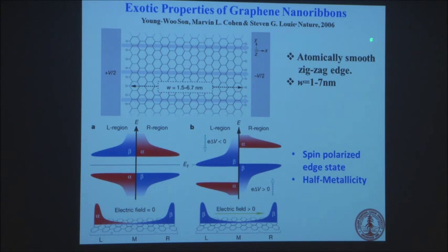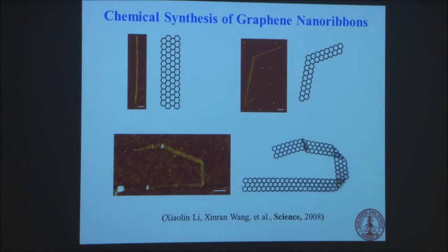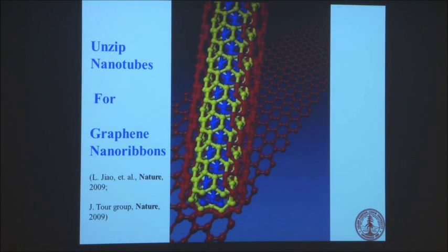So this got a lot of interest many years ago now, but even to this day, this was not seen experimentally, because we don't really know how to make such a ribbon with such perfection. So that's what got us interested in the beginning. So in 2008, my group made some ribbons, and these are shown here. It's a very simple process, but over the years, we really tried to improve the synthesis, including this way of opening up a nanotube. A group at Rice, Jim Tour, and us did the same thing pretty much. Open up nanotubes to make ribbons, and it does work.